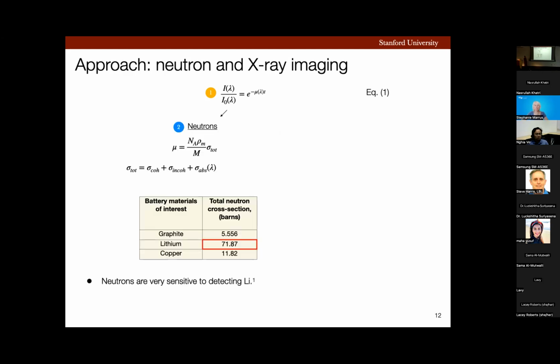Now, for neutrons, this mu is directly proportional to sigma total, which is the total neutron cross-section. It is a summation of coherent scattering, incoherent scattering, and absorption. Now, let's look at this table. You can see that its value for lithium is very high and that for graphite is low. Thus, neutrons are very sensitive to detecting low Z materials such as lithium, especially on graphite, because of the relative neutron contrast of the two materials with respect to each other.